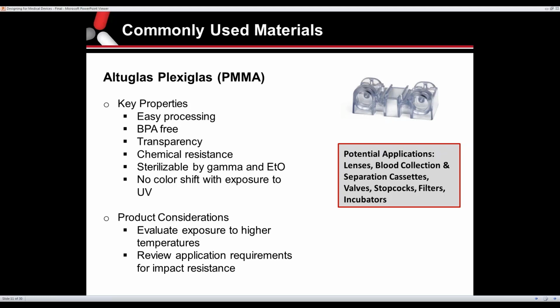It does provide good chemical resistance. It can be sterilized using gamma and ETO. The other added benefit is you don't see a color shift when exposed to UV. So if you have a component that's going to be exposed to UV light, either in use or through filtered light, this is not going to shift colors on you because of the UV exposure.